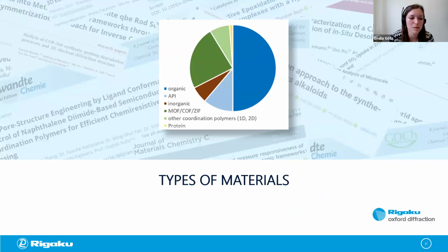So we've already seen some examples on which kinds of materials the Synergy-ED was used, but here's a general overview again. We can see that about half of the structures published were organics, mainly small molecules, and if we also count APIs to that, which I've listed separately in this case, then it's an even bigger part. The second biggest part is MOFs or MOF-like structures, and then we also have a certain amount of inorganics and a small amount of proteins.